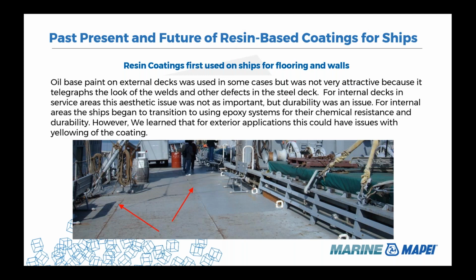Looking at the oil-based paint, on exterior decks it was used in some cases, but it wasn't very attractive because, as you can see in the photo, you can see the seams in the deck where the welds occur on the metal. Now, when you paint a deck, obviously, you can see whatever's underneath that paint unless you do something to smooth the area. In an internal area that was maybe for service, this is not an issue with aesthetics. But durability with a single coat oil-based paint really wasn't very good.